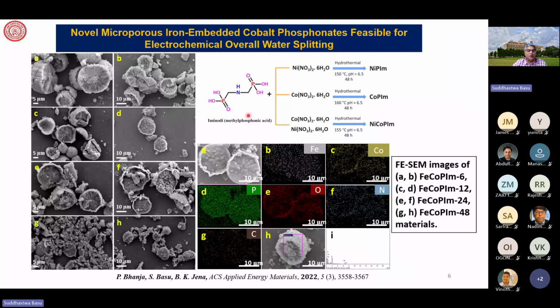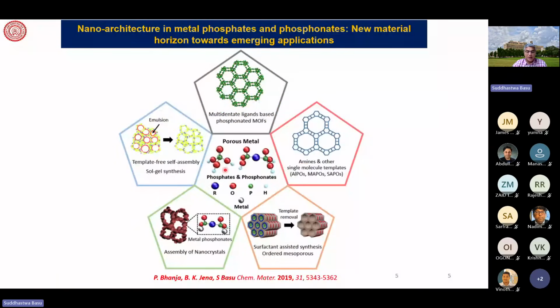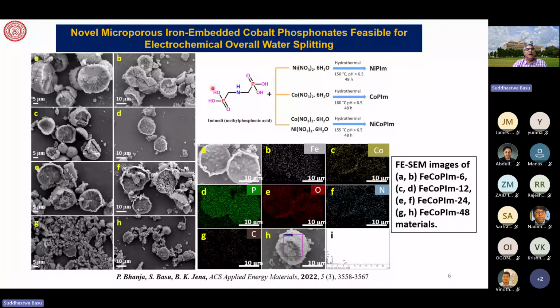It is a template. I was showing you that this is the template, and a similar template is shown here, and with that we add nickel nitrate, or we add cobalt nitrate, or we use nickel cobalt nitrate, and we do a hydrothermal synthesis. You could put them in a reactor or a bomb autoclave, and then we heat to a certain temperature and pressure and maintain pH for certain hours, and we get a nickel phosphonate, cobalt phosphonate, nickel cobalt phosphonate. We also add iron to that.